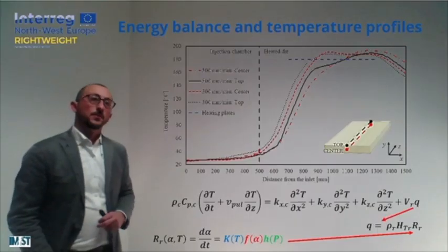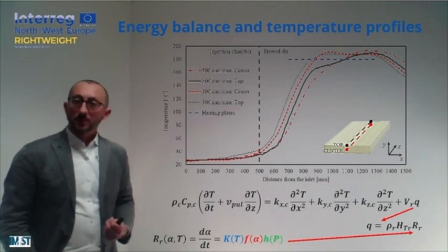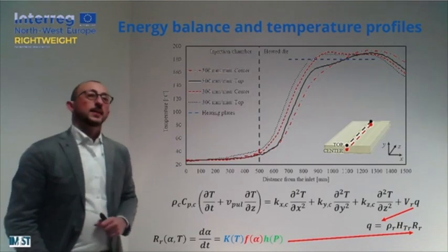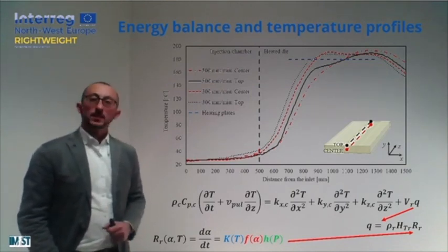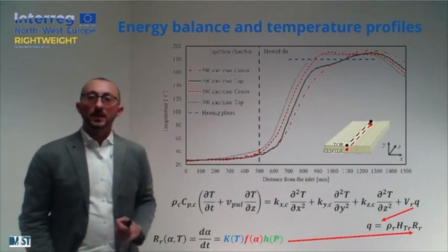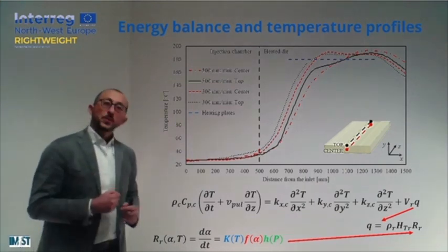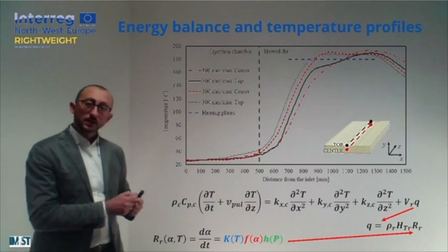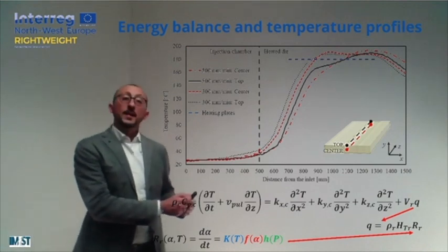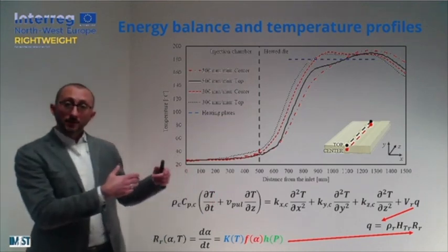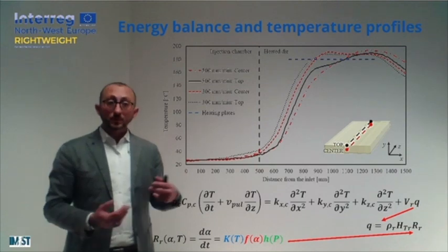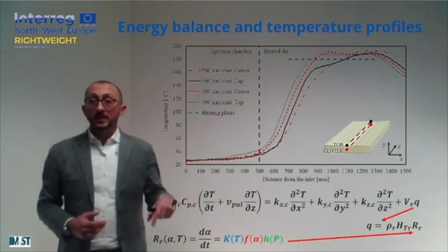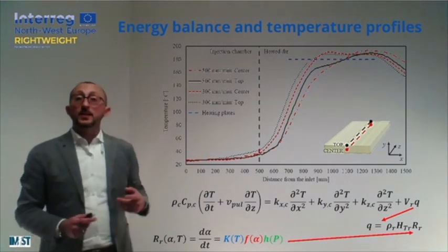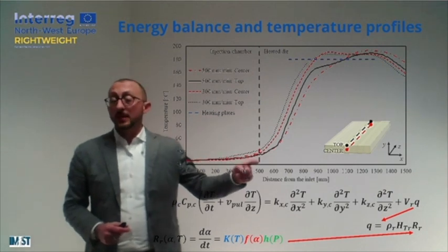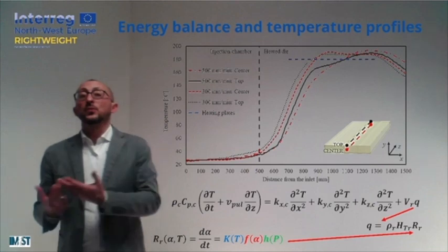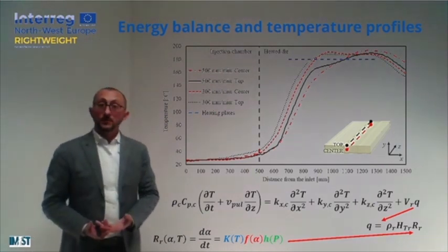In this figure, we can see some temperature profiles that are collected inside a composite material during pultrusion using the so-called traveling thermocouple technique, meaning that a thermocouple is connected to the fibers and will travel inside the injection chamber and then the heating and curing die, collecting at each time instant the temperature that is experienced by our material inside the die. Looking at this figure, we can see how the temperature inside the injection chamber is typically low due to the cooling effect that we were mentioning a few minutes ago.